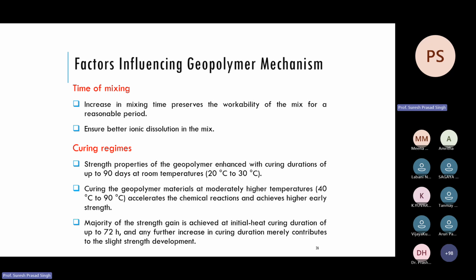Then the curing regime. So geopolymer can be formed at any temperature, ambient temperature and all these things. But it is found that initial heat curing is very beneficial for the strength and durability of this material, which we will be discussing. Most of the research papers say that the initial 72 hours, that is, 3 days of heat curing, and after that ambient curing, maybe 20 to 30 degree curing, will give you good strength.